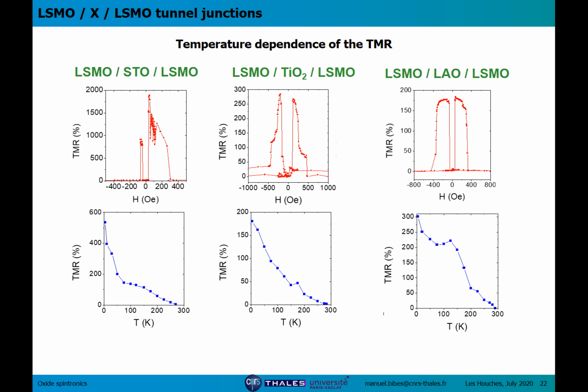Now let's have a look at the temperature dependence of the TMR. These are some results from our group. We combine electrodes with different tunneling barriers: strontium titanate, TiO2, lanthanum aluminate. All this is at low temperature, typically 4 Kelvin. We have TMR reaching a few 100%, maybe 200% for LAO. In some junctions, you had even more than that, up to 1000%, if I remember. But if we measure the same curves at different temperatures, we see that the TMR for all three systems decreases with temperature and becomes basically zero at room temperature. So this is quite disappointing.